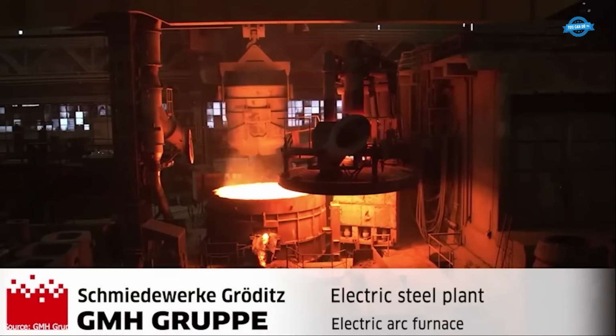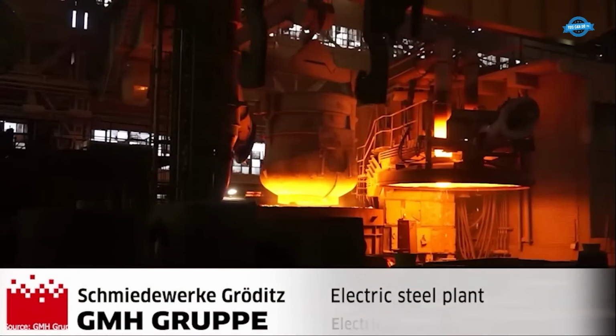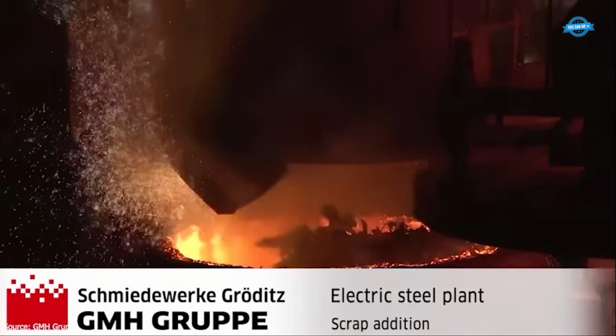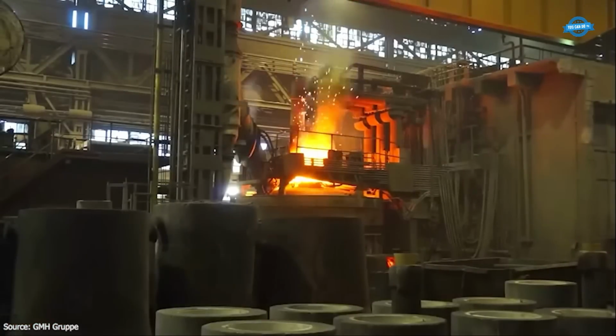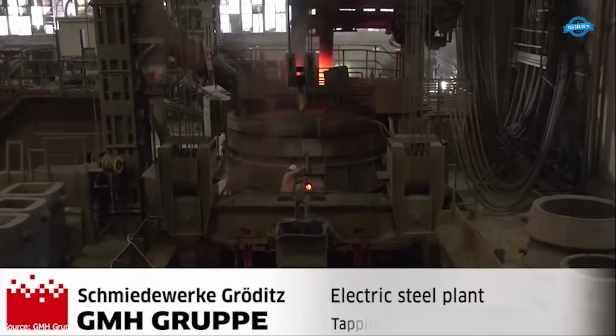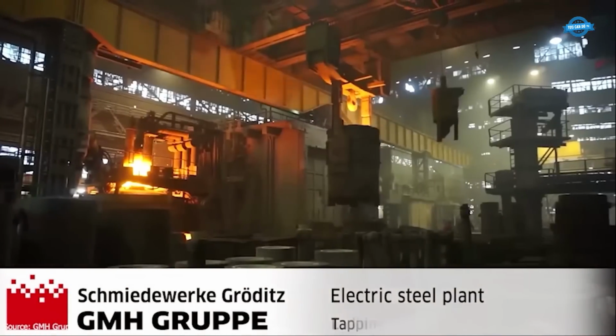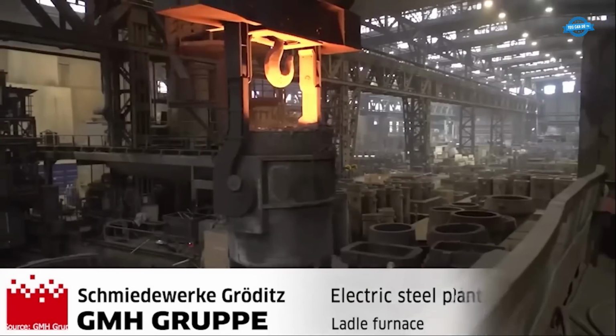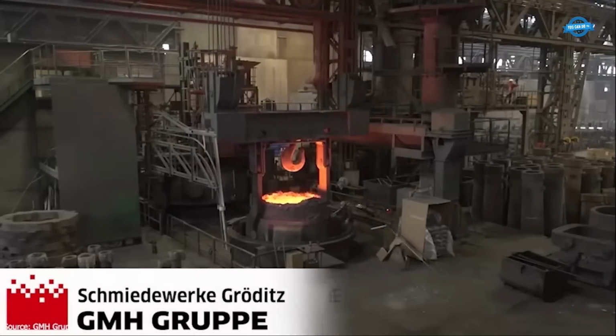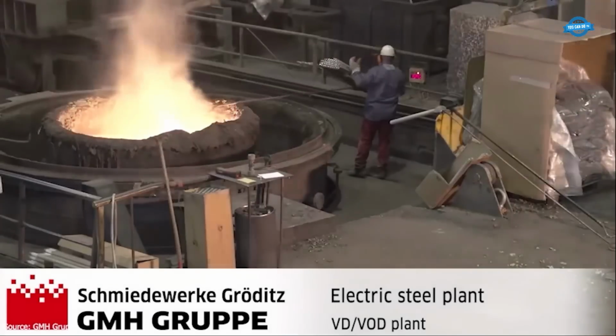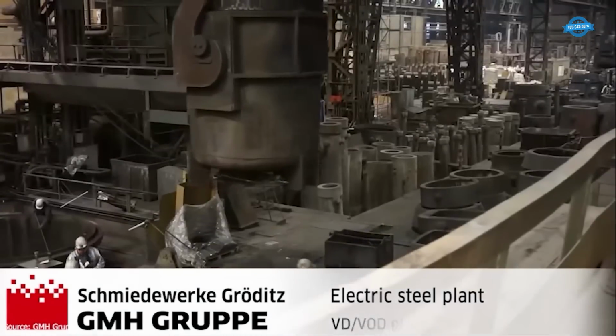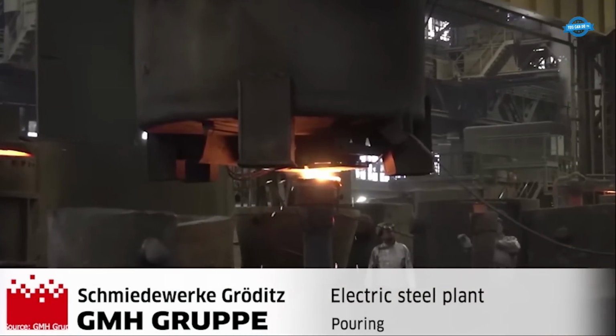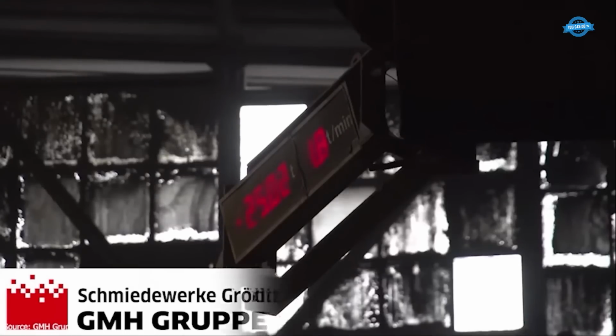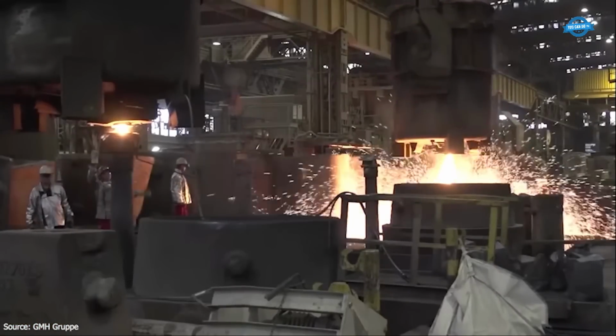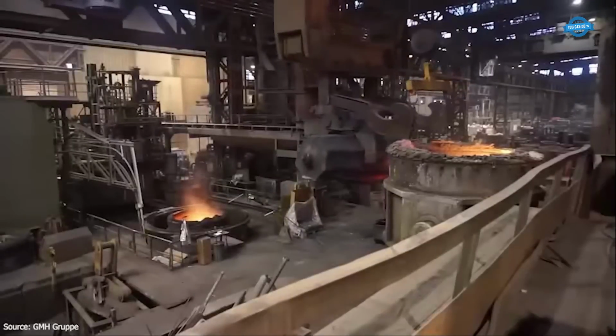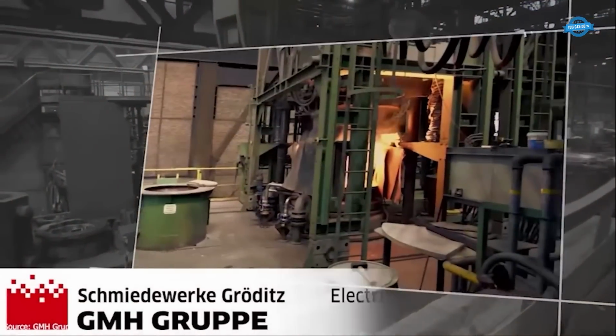Schmiedewerke specializes in forged products for the mechanical and plant engineering industry, operating an electric arc furnace that produces up to 50 tons of liquid steel per load. The process starts with 100% sorted scrap, melted and tapped, followed by precise temperature and alloy adjustments in the ladle furnace. In the VD or VOD units, dissolved gases are removed to ensure material purity.